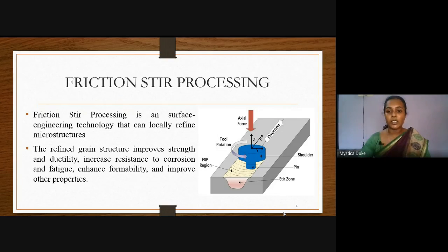We do this by taking a third body, which is a non-consumable tool. In the friction stir processing machine, the non-consumable tool moves along the surface of the material, which is AZ31 here. The tool rotates by itself and moves transversely on the surface. Because of this rotation, it causes plastic deformation by the stirring action. Because of this heavy rotation, friction develops between the tool and the workpiece, and heavy heat is developed. Due to this plastic deformation along with the heat, the stir zone is developed in the material.